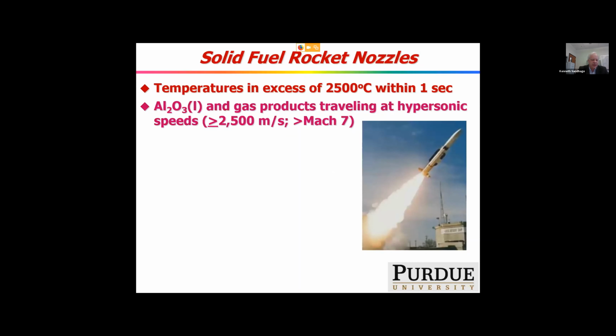So when you think about thermal applications and extreme thermal applications, it doesn't get much more extreme than solid fuel rocket nozzles. On the back end of a solid fuel rocket where the nozzle exists, the temperatures can soar from ambient to over 2,500 C within a second, extremely thermal shock prone. A common type of solid fuel propellant is aluminum powder mixed in with an organic matrix. You ignite the aluminum, it oxidizes, gives off enormous heat, burns the organic, and the aluminum oxide liquid and the gas products travel through the nozzle at hypersonic speeds, over Mach 7.